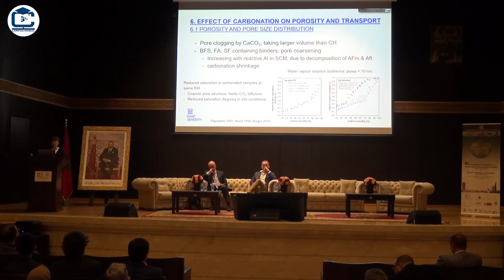So actually what I already mentioned is that carbonation produces calcium carbonate, which takes a larger volume, so you get some pore clogging. On the other hand, the SCMs might lead, when there is carbonation, to some pore coarsening because you start carbonating the CSH. If you have aluminium in the SCMs, this might also have an effect, and also carbonation shrinkage might come into the picture.